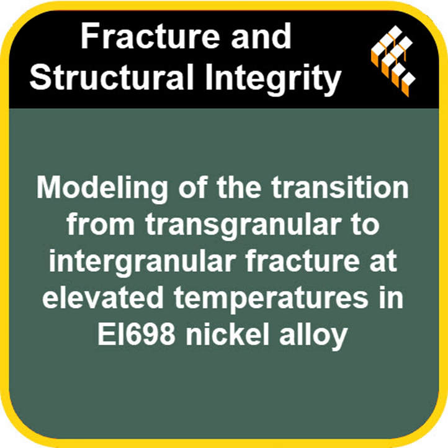Precisely. Without it, the model might predict cracks forming where there's just significant plastic bending or stretching. They found that dissipating about 90% of that plastic energy as heat, rather than using it to drive the crack, was necessary to get accurate predictions of the macro crack growth path, as shown in Figure 9. Wow, okay. That sounds like a really important detail to get right.